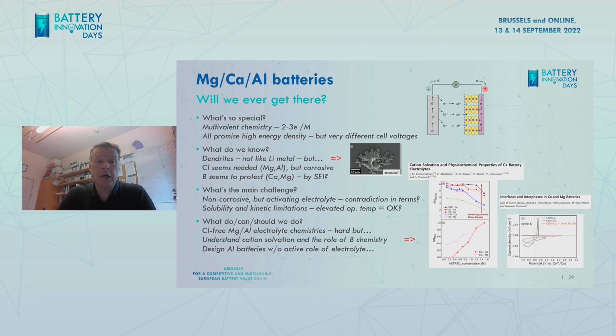So the main challenge comes back actually to this thing, that when we're talking, for instance, that chlorine seems needed. You need a non-corrosive electrolyte, but it still needs to be able to activate your surface, and that seems to almost be a contradiction in terms. Of course, it's not really that, but it seems to be.